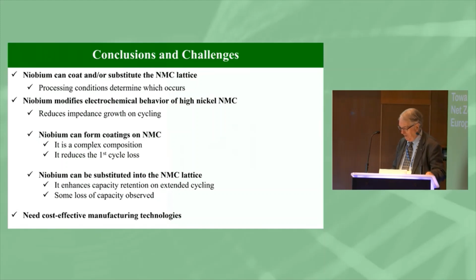So a few concluding remarks. By controlling the processing conditions, we can put the niobium on the surface, or we can substitute the full lattice. And the niobium actually modifies the electrochemical behavior, stops these surface films being formed, and stops the impedance growth on cycling. We know we can form coatings on the NMC. It's a complex composition, but it does reduce the first cycle loss. Having made the substituted materials, we're now going to see if we put a coating on that substituted material, whether that will give us additional benefits. We see some loss of capacity when we substitute it, but it's not obvious we're seeing that with others.